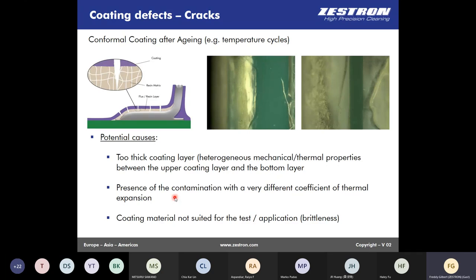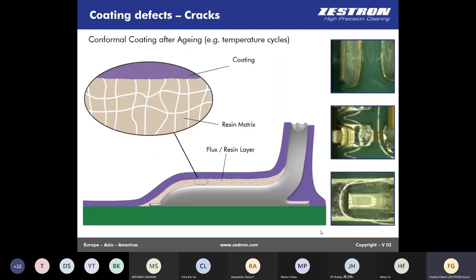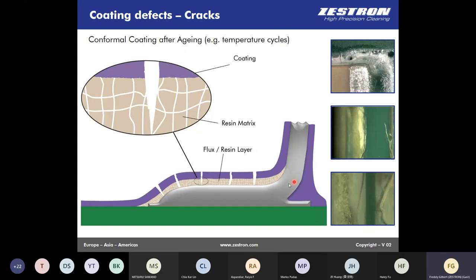In most cases it is recommended to clean before coating to avoid problems with resin residues, or at least in no-clean approaches to reduce residues from the solder process as much as possible. Another cause of early cracking is that the coating material is not suited for the application and becomes too brittle through successive thermal stress — in that case another material should be used. Right after coating application, the area is perfectly closed, and after stress we see cracks opening as entry ways for water or harmful gases.